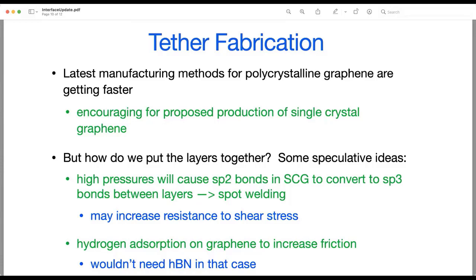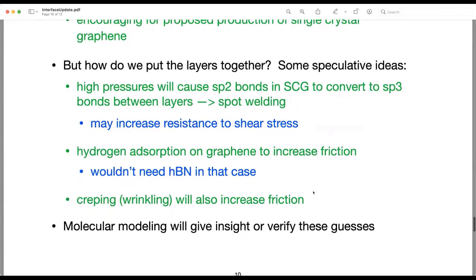So how do we put these layers together? So there are some speculative ideas that we've talked about in our study. And one very neat idea that Adrian proposed is that we can use high pressure to create the normal bonds, that is the sp2 bonds in single crystal graphene, to convert to the sp3 bonds between layers. And sp3 bonds are basically the bonds that you find in diamond. And so if we locally put high pressure on the laminations of the tether, we could perhaps press them together, force some of the bonds to be diamond bonds, and then we can increase the resistance to shear stress. So that's a really nice idea, but it really needs more exploration.